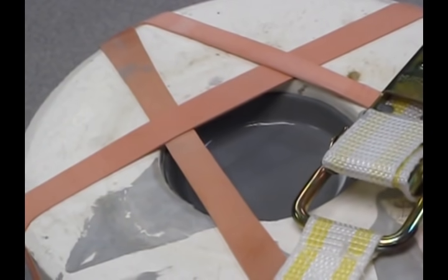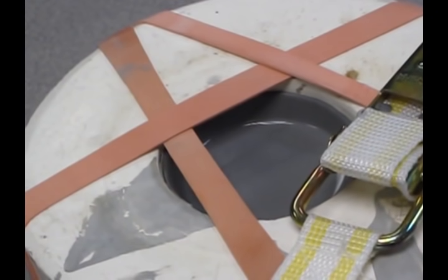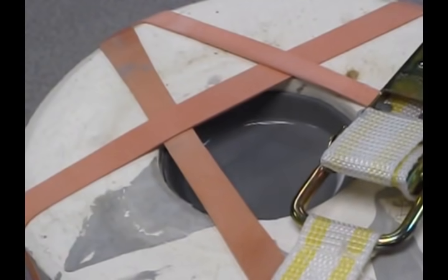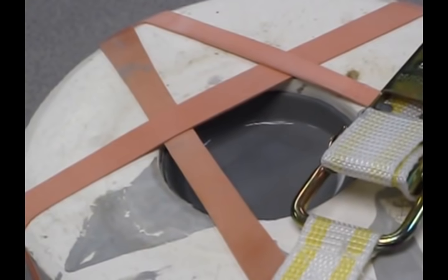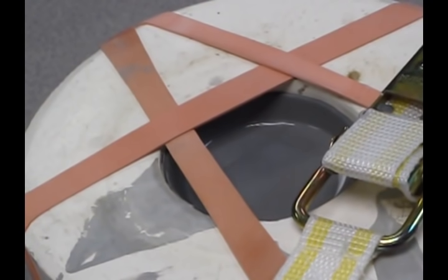The slip has been left to rest in the mold for approximately 45 to 46 minutes, and you can see that in that time, the moisture was wicked out of the slip and pulled into the plaster of Paris.